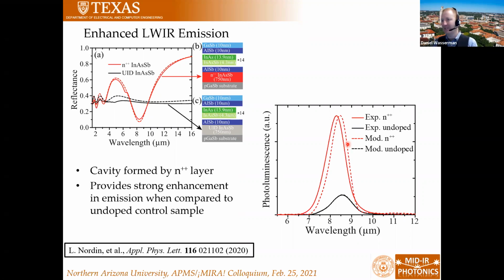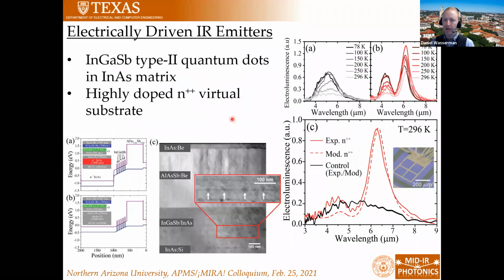So what that means is it's effectively lost because there's nothing to scatter it to free space. So it's just propagating along and getting absorbed. But even so, just the cavity effect is enough to see a significant enhancement in emission. And remember, this is the exact same emitters, just a slight change in the substrate.